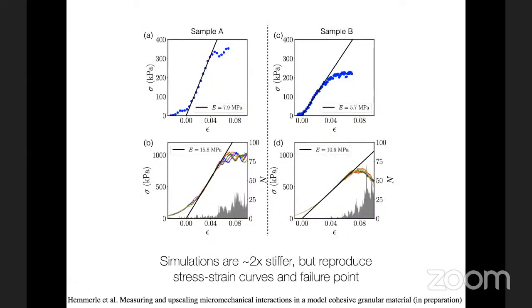These are two experimental stress strain curves to show the comparison between them. The experiments are on the top, the simulations using the same material properties and the same coordinates of the particles are on the bottom. We find that pretty much everything works the same way, with the exception that the simulations are about twice as stiff. We attribute this to the fact that in the simulations, we're making all the bonds the same stiffness, whereas in the experiments, we know that if particles are a little bit further apart, the bonds between them will have a lower spring constant. So we're not taking that variability into account. And that's what we believe is making the difference in the factor of 2 between the stiffnesses.